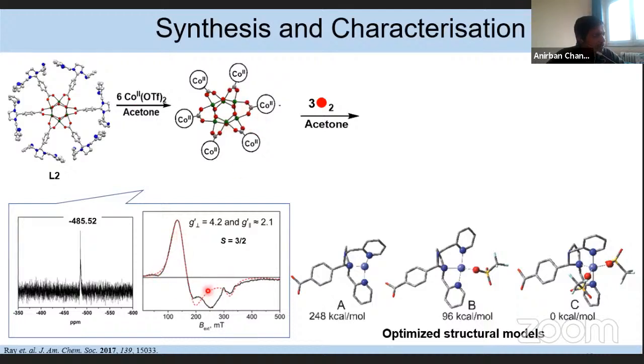And EPR data also shows a high-spin cobalt(II) signal with S equal to 3/2 spin state, which also confirms that the cobalt(II) centers are not interacting among each other, and there is no intramolecular interaction between the cobalt centers. The DFT optimized structure again suggests a 6-coordinated structure of the cobalt(II) with 4 nitrogen atoms from the ligand and 2 triflate anions.